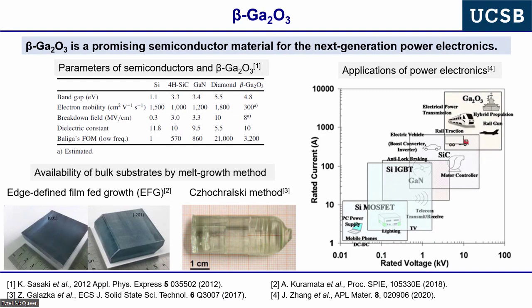And I'll explain some issues with diamond in just a few moments for you. What makes beta gallium oxide remarkable, and this is why I'm so interested in the work going on here and at Michigan and elsewhere in germanium oxide, is that beta gallium oxide can be grown directly from the melt. I think the bandgap of gallium oxide is just a hair larger than rutile germanium oxide. So I think it's a fair statement that beta gallium oxide is the widest bandgap semiconductor that can be directly grown from the melt.